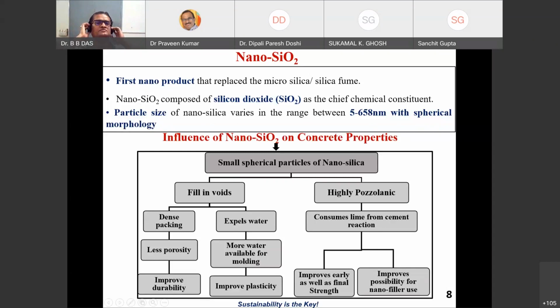Well, nanoscience is between 1 to 100 nanometers, but it is difficult for us even using 100 nanometer size particles. So researchers have used 200 nanometers, 300 nanometers, even up to 500 nanometers. But most of the morphology is found to be spherical. Spherical morphology is ideal for my cementitious system or for my hydration. When we produce nanoparticles, the ideal is the spherical morphology.